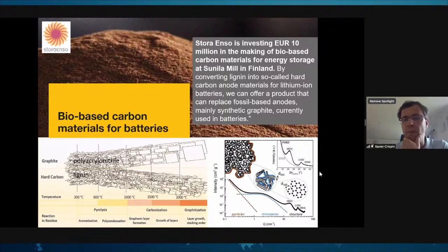So in that case, you form particles, and those particles have graphitic planes that are formed, but it's not a perfect single crystal, far away from that. You have small graphitic nanodomains as well as some other voids. So it's not as clean a material as a good graphite, but it is good enough. It conducts electricity, and you can store a lot of energy with ions in it. So this is basically using lignin and making carbon out of lignin, which is nice, but it would be